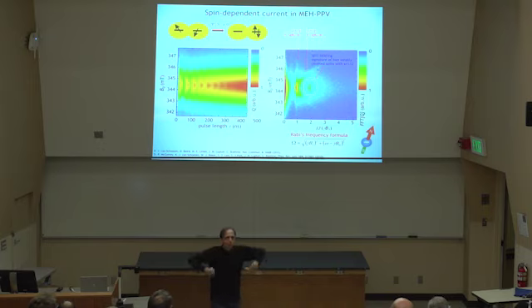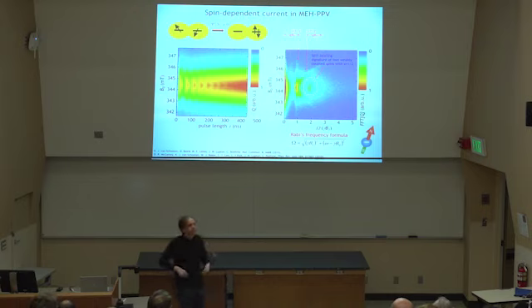If you turn both at the same time, then your electronic transition rate is governed by the beat oscillation of these two spin nutations. And beat oscillation is the sum and the difference of the individual frequencies. That's exactly what you see here. And in fact, something that you see when you get frequency components close to 0. So we can literally do spectroscopy with the spin Hamiltonian.